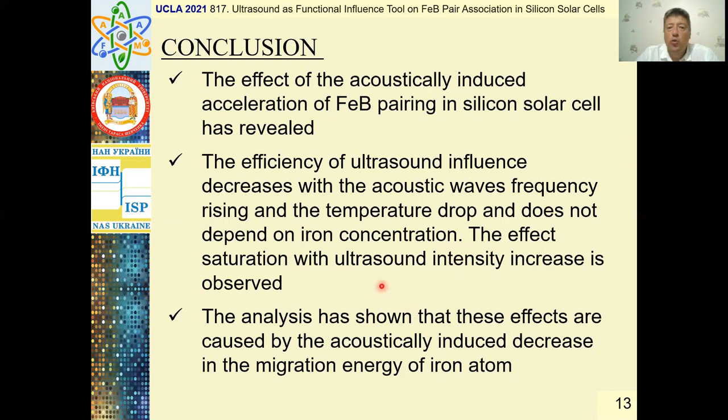The effect saturation with ultrasound intensity increase is observed. The analysis has shown that these effects are caused by acoustically induced decrease in the migration energy of Iron atom.